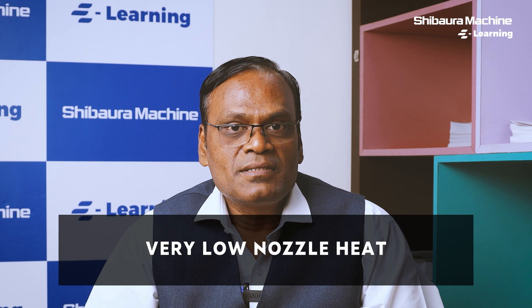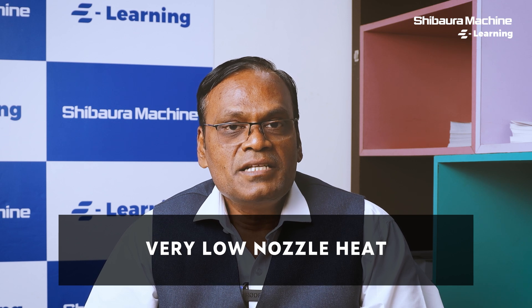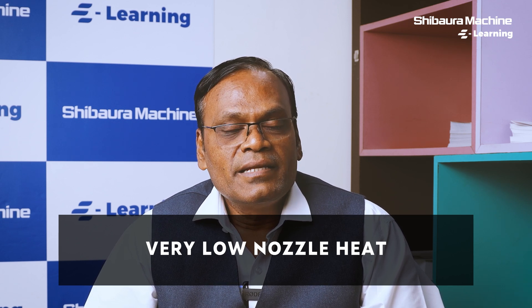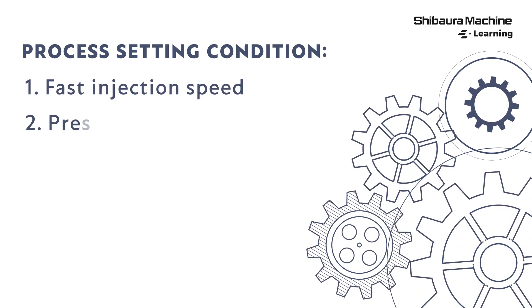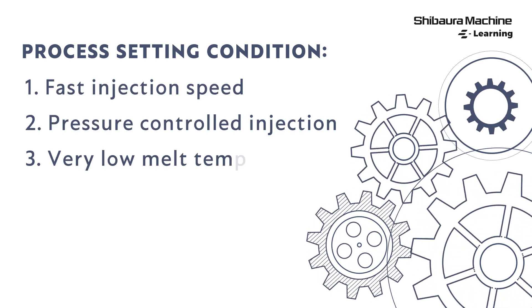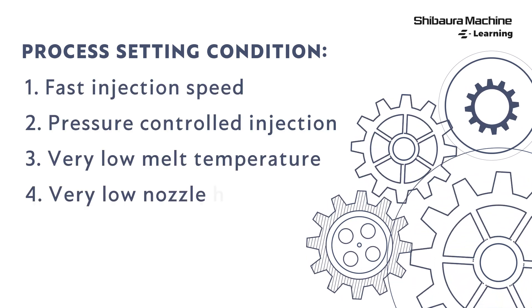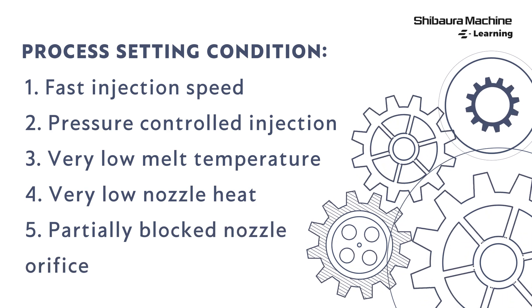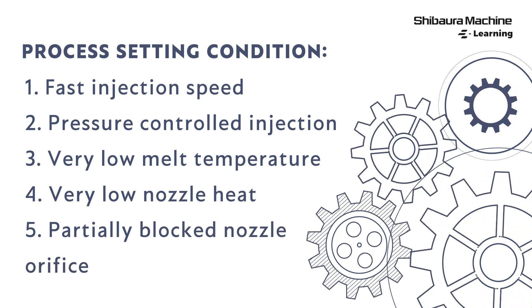When the nozzle temperature is too low, a cold slug forms, which also leads to jetting in the molded part. While setting the plasticizing cylinder temperature, due consideration must also be given to the nozzle temperature to avoid cold slug formation and prevent jetting. When setting the process parameters, proper consideration of temperature, injection pressure, and injection velocity results in a jetting-free molded part.